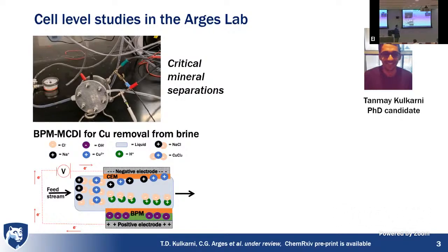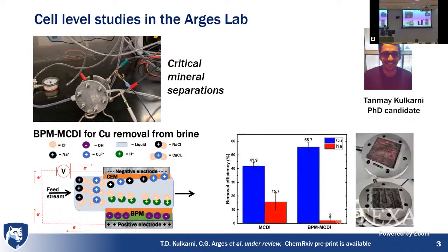And this is where we use two porous electrodes. We can electrically bias them and we can pull ions out of a liquid stream. But in this context, we were looking at copper ion removal. So this copper is diluted with a brine solution and collecting it on an electrode with this bipolar membrane. So this bipolar membrane is useful because we can do in situ pH adjustment while we're taking the ions out of solution.